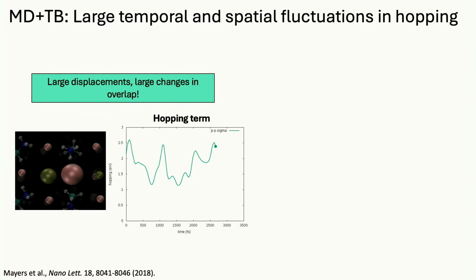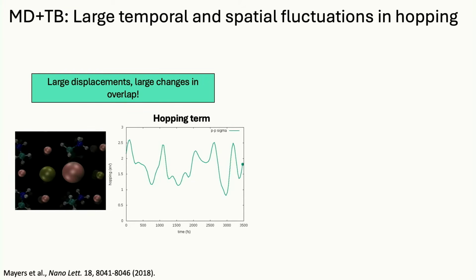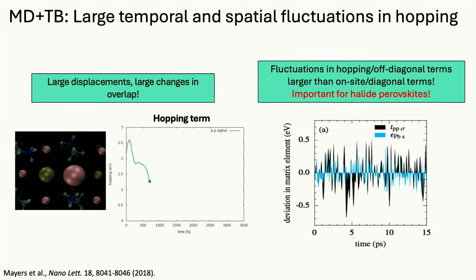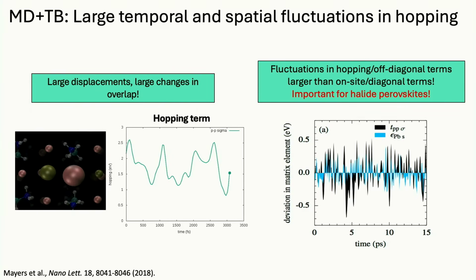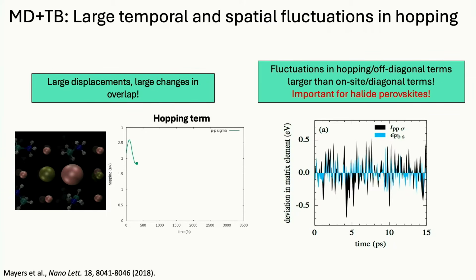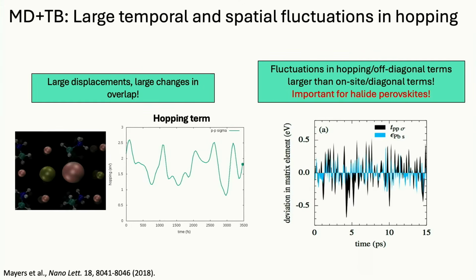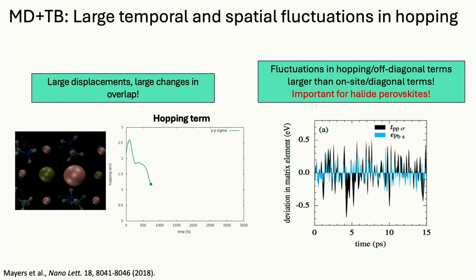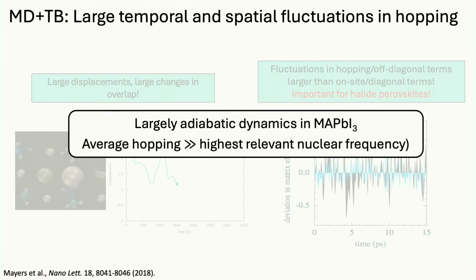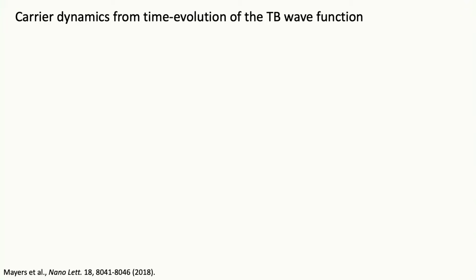If they can't go this way, they go another way. So you should have a picture that the electrons are not just having a smooth time getting through the material. That's what that's telling you. And then the on-site energies. This is just the energy of residing on a lead. Sometimes it's high, sometimes it's low. You can see the blue parts are also wildly fluctuating. So what this means is sometimes the electron's happy over here and the hole is happy over there. Then they scatter. Sometimes you scatter this way, sometimes you scatter that way. But the electron and the hole will never be happy at the same place at the same time. So the electrons and holes are dramatically scattered, but always away from each other, you see? So this dramatic ion motion leads to a very long carrier lifetime. They were always scattering the electrons and holes away from each other.